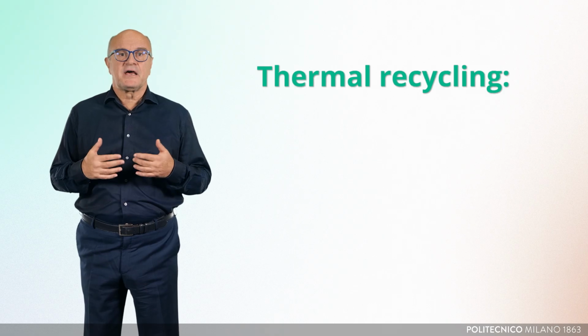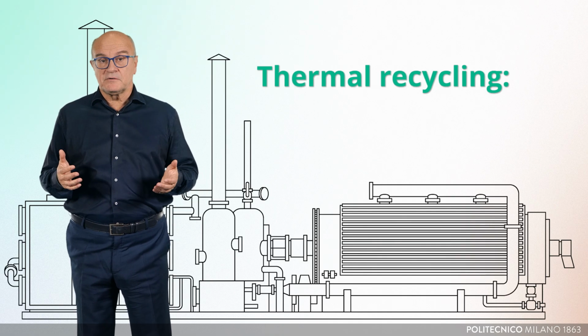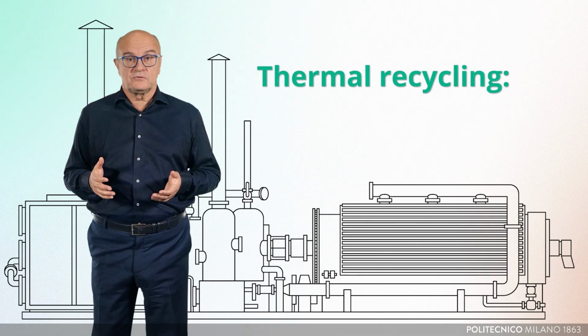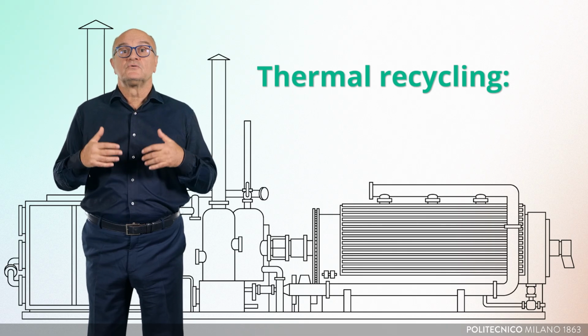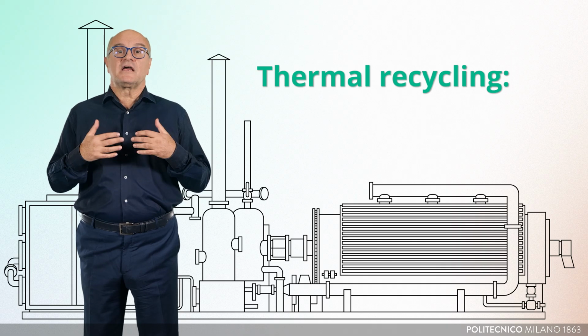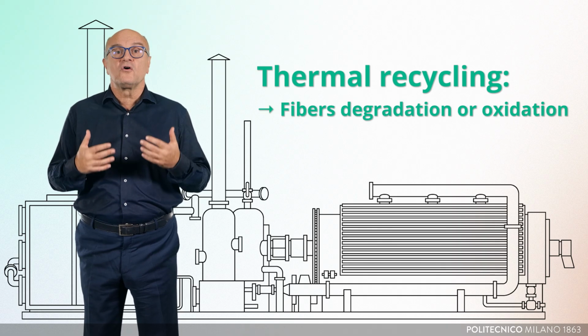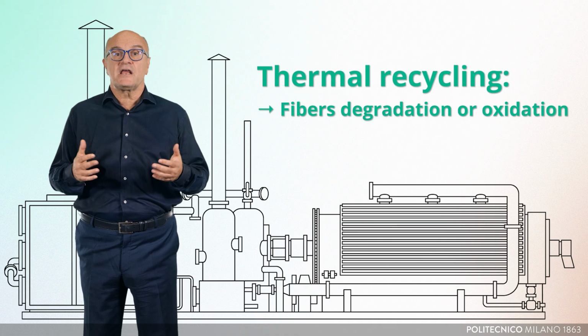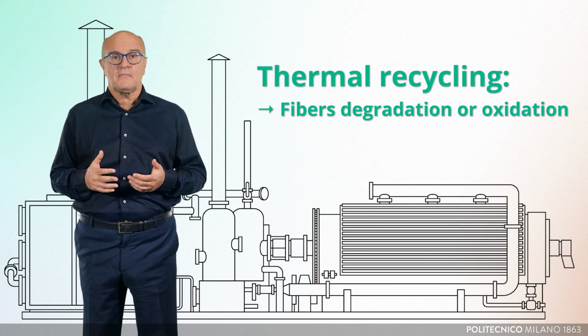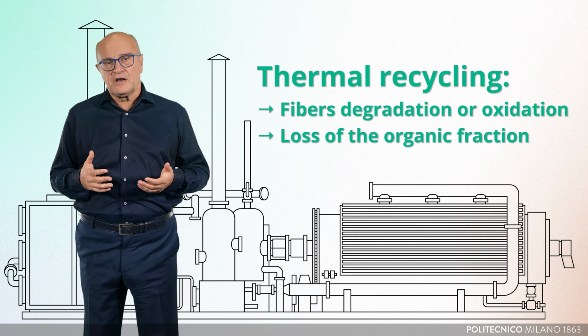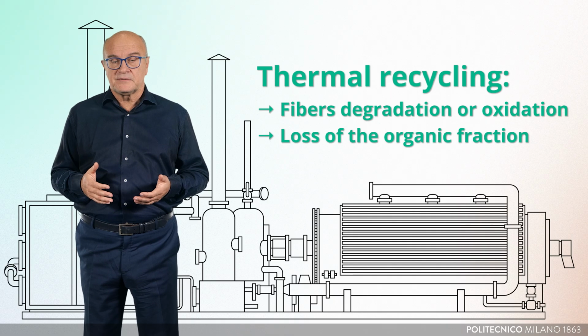Thermal recycling, like pyrolysis, breaks down the polymer backbone and evaporates the decomposition products at high temperatures to recover fibers. However, the heat treatment degrades glass fibers and can oxidize carbon fibers while generating dangerous emissions. Moreover, the organic fraction is often lost or only partially recovered, making this method not fully compliant with the principle of a circular economy. In general, both these methods fail to reclaim high-purity monomers or intact fibers.